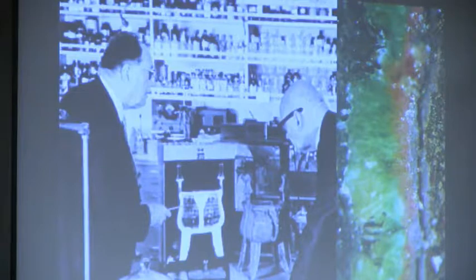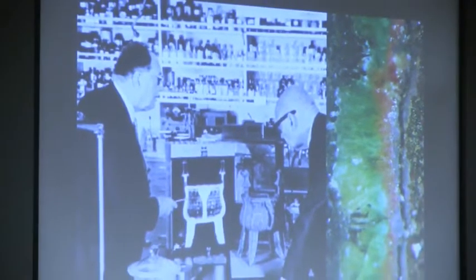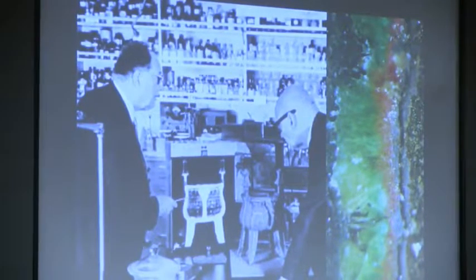From the right edge, you have the bronze and then cuprite and malachite, with the oxygen-poor cuprite closer to the bronze. He was very interested in what was characteristic versus what might be an artificial patina at the time. And again, this is in the 50s, 60s, so it's quite early.